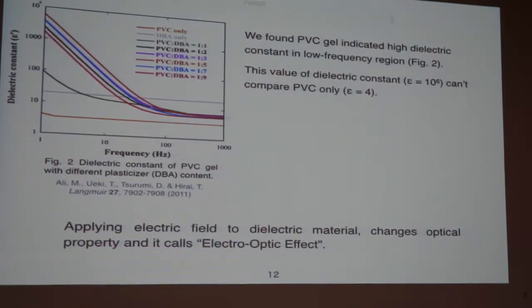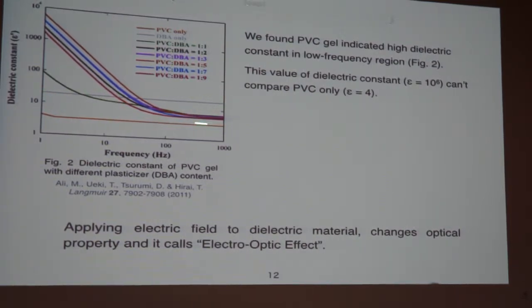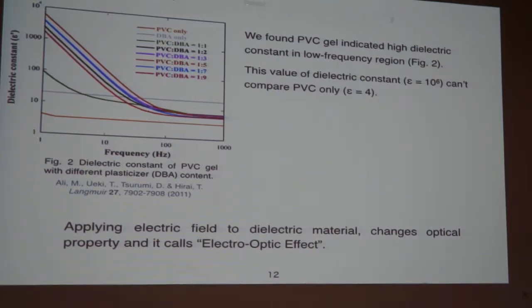And the reason is shown in this way. When we carry out a frequency analysis, this is the polymer, this is the plasticizer. By mixing them, the two components don't show any large dielectric constant. The dependency on the frequency is very low. But when we mix these two compounds and make the gel, it is a total change. A huge increase of the dielectric constant is observed.